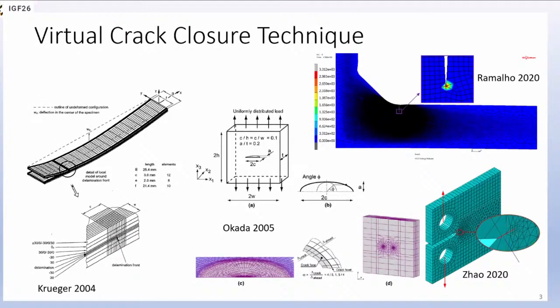VCCT is a local analysis technique that allows the evaluation of the stress intensity factor in the presence of a residual stress field. This technique has been extensively applied in the analysis of delamination processes, mainly in two-dimensional models. Recently, we have used this technique in T-joints to evaluate the effect of residual welding stresses on the propagation of cracks in the weld toe using two-dimensional models.